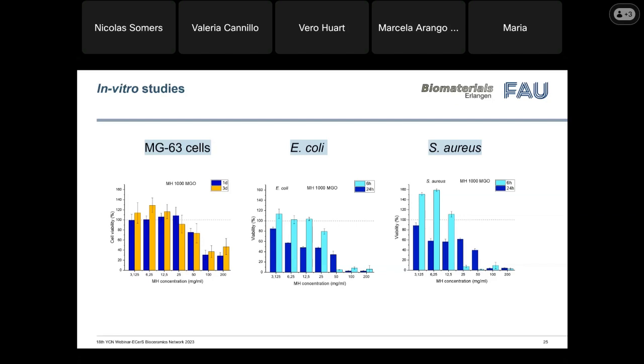And then we continued trying to combine different concentrations of honey and also different concentrations of the dissolution products from glasses, and then analyze if we could observe a synergistic effect when we combined both. In this case, we were not using scaffolds anymore. We were just using the dissolution products of the glass. But the results are in preparation for publication.